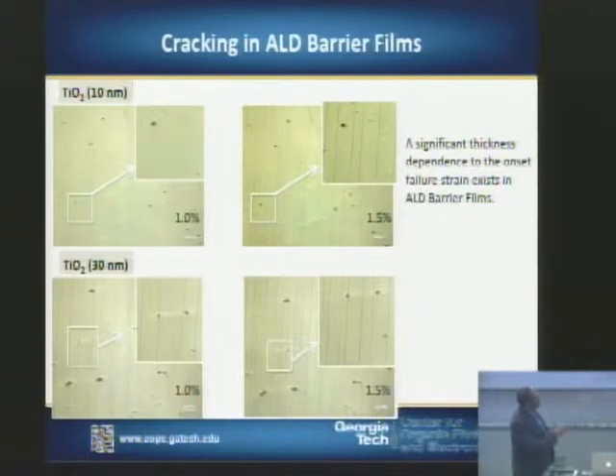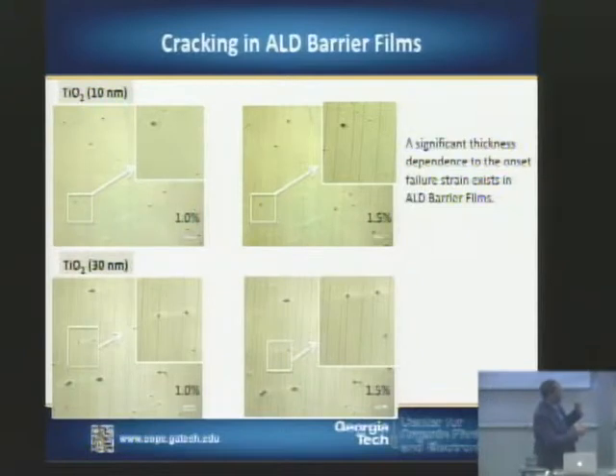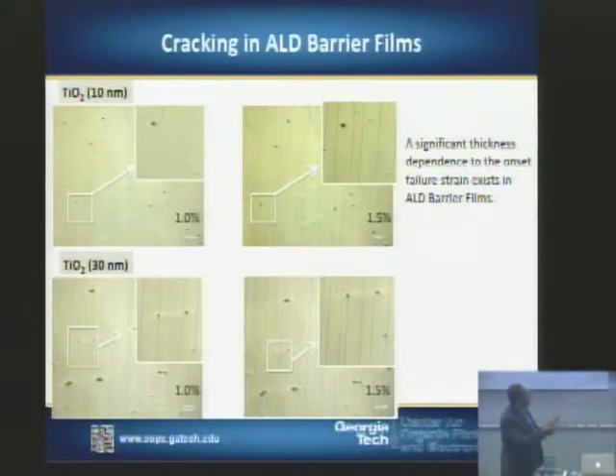If I go to a 30 nanometer thick film, you can see now at 1%, I have quite a few cracks in the film. And so there's a strong thickness dependence to the crack driving energy in these particular films. So this also states that not only do you want to have the film thin from a manufacturing point of view, but you also want to have it thin from a mechanical compliance point of view, or a mechanical reliability point of view.